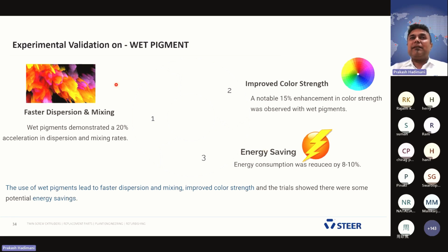After doing the experiment, we validate what is important using wet pigments. When you use wet pigments, you get faster dispersion and mixing. Wet pigments demonstrated a 20% higher and faster rate of mixing compared to dry pigments. And what's the improvement in color strength? 15% higher color strength compared to the dry pigments.